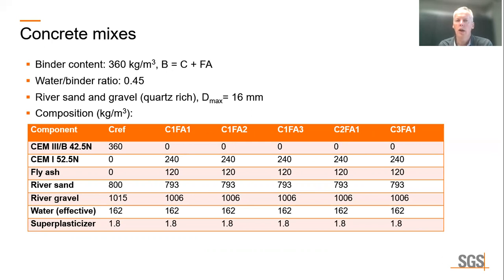We used river sand and gravel with the maximum grain size of 16 millimeters. And the fly ash content in the concrete mixes was 120 kilograms per cube, and the Portland cement content 240 kilograms per cube.